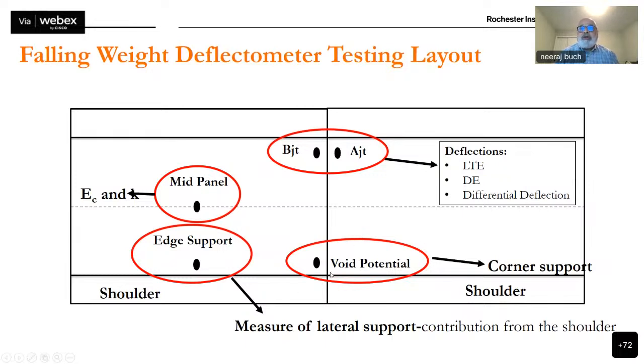And then you can also measure the possible voids under a concrete pavement. The voids could be due to erosion, poor compaction, or poor construction, and the falling weight deflectometer allows you to measure, or at least predict or estimate, the possibility of voids that exist under the concrete pavement. So the falling weight deflectometer is a very versatile tool where you can calculate, in a very short period of time, the structural integrity of a concrete pavement or an asphalt pavement.